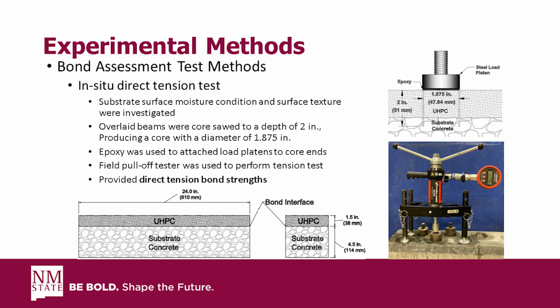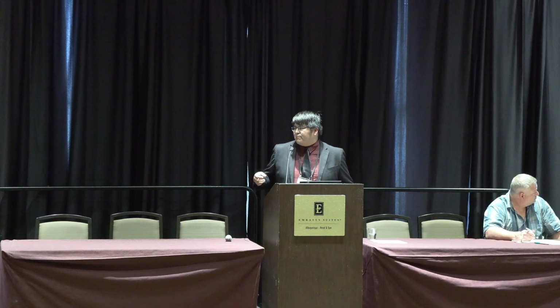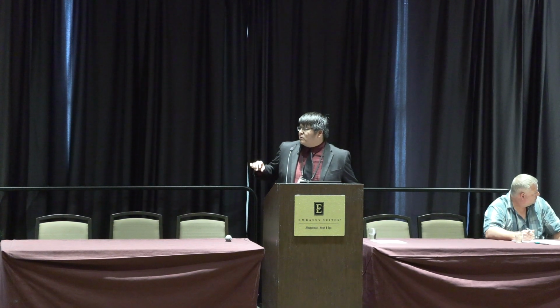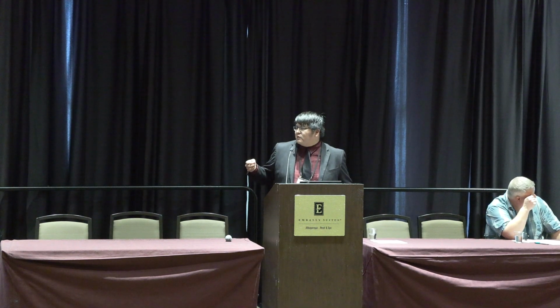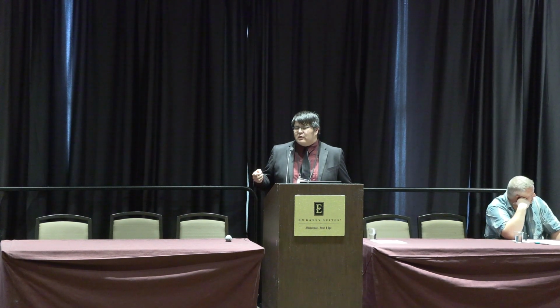And so here's an in situ direct tension test. We call this in situ just because we don't completely core out the specimen. You can see in the top right image here, we core down into the specimen with a core saw bit that's about 1.875 inches in diameter. We core down about 2 inches, so 1.5 inches past the UHPC overlay and about 1/2 inch into the substrate concrete.